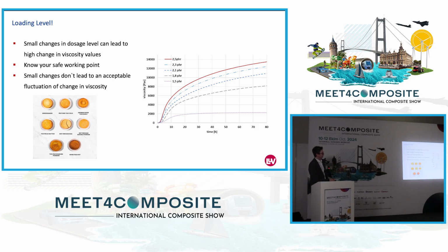Changing the amount also leads, you see again time versus viscosity, to totally different results, from really fast to absolutely slow. There are, of course, also some limits. You cannot go over a certain level, then nothing happens anymore, and you cannot go lower. This is important because from time to time we get the remark that the thickening is totally different. And when we ask the people, do you level it out always at the same time? They said, no, we just have one guy with a bucket who grabs a little bit and puts it in. It's roughly the same. But this is already leading to totally different thickening performances.